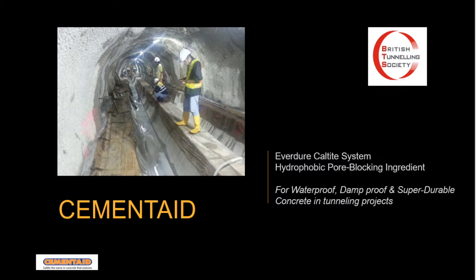Has the system ever been used with shotcrete? Yes, it has. As I said, when we looked at the Bear Creek Tunnel in Colorado, that was shotcrete. It really depends on the efficacy of that. Really depends on the skill of the nozzle man. It's not like placing normal concrete or even self-leveling concrete these days. It does require a fair degree of expertise from the nozzle man. But yes, it has been used. If it's properly placed and there's no voids behind the steel, it will work beautifully.